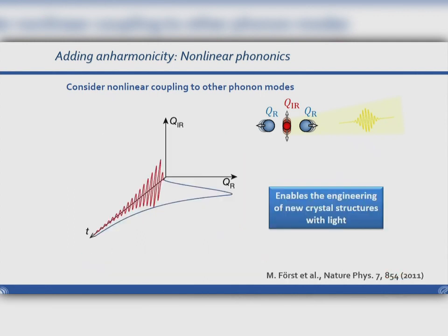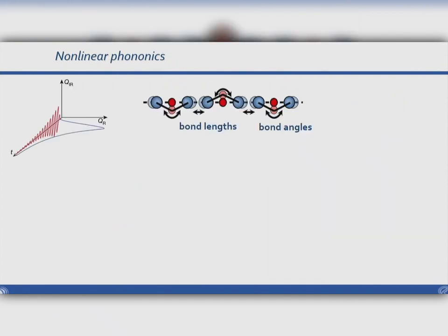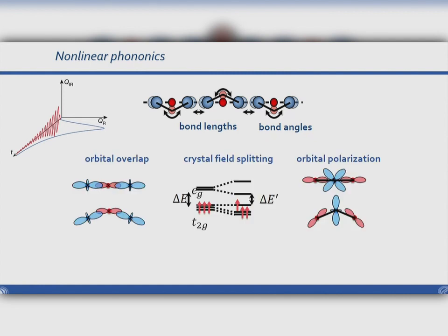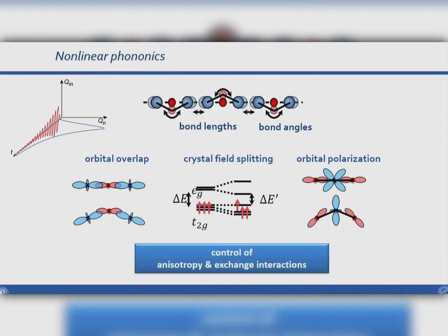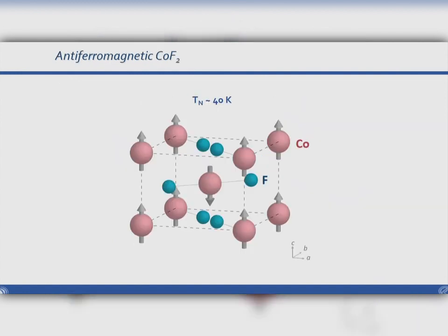And indeed, this is the idea of this scenario. So while this IR mode is ringing, you have a displacement of the lattice along the coordinate of the IR mode, and this enables the engineering of new functional properties. For example, in this way, you can easily transiently change bond lengths or bond angles, and in that way, you can control orbital overlap, you can change crystal field splittings, orbital polarizations, but on the other hand, also you can control anisotropy or exchange interactions. So there's a whole zoo of phenomena that you can induce now, and this allows us to induce all the changes that I've introduced to you before.